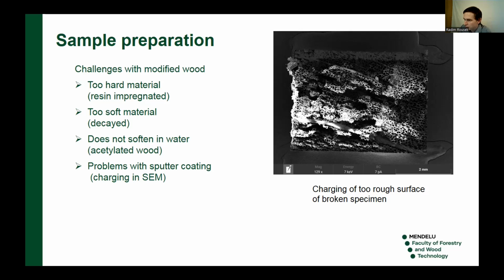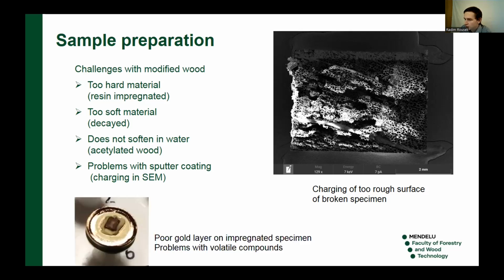The other problem with sputter coating could be volatile compounds. If we have impregnated material, there could be some low volatile compounds, but still, if there are some, it could influence the deposition of the gold during sputter coating. You can see this stub with a very small wood sample, and you can see the stub is very well coated with gold, but the layer of gold on the sample is very poor. The solution for this problem is either remove the volatiles, or a good solution is to make the sample as small as possible. It helps with charging in any case.